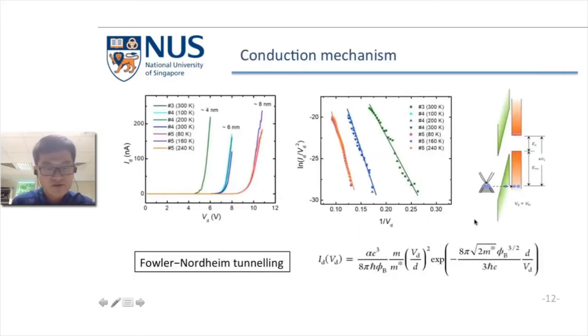To further verify our conductive mechanism, we measured the temperature dependent conductive curve of flakes with different h-BN thickness. First, we found that the IV curve is temperature independent, which is consistent with tunneling behavior of the conductance.